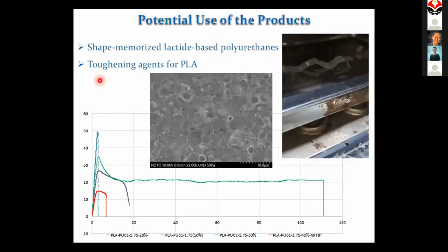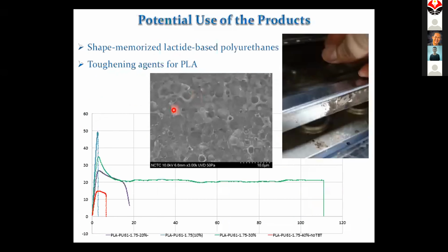Or we can use this as a toughening agent. We know that PLA is brittle. If we look at mechanical properties, PLA can break very early, around 4% elongation. However, if we add our polyurethane into this PLA, we can make it go much longer before breaking, right? The elongation can increase to more than 100%.